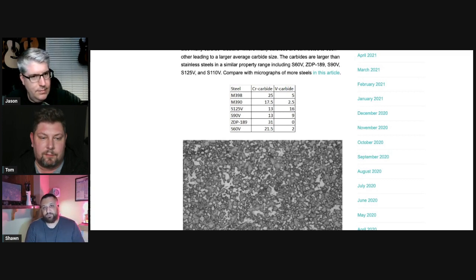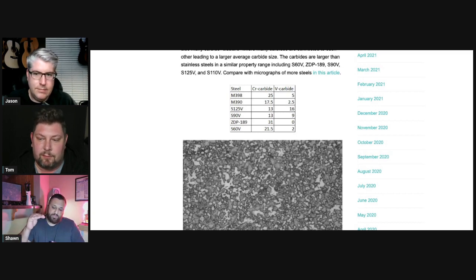So that's kind of how detailed it's working. It's kind of confusing. It's not intuitive. Right. You have to have some background information to know how much volume is inside the steel, because it's not from looking at the chemistry of the steel that you know exactly how much carbide volume there is. So if you see 10% vanadium, it doesn't mean that there's 10% carbide volume. There's 17% in 10V.